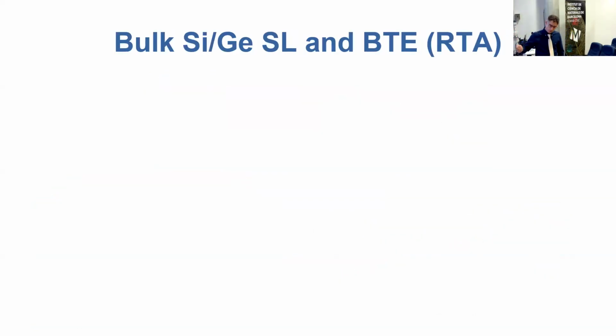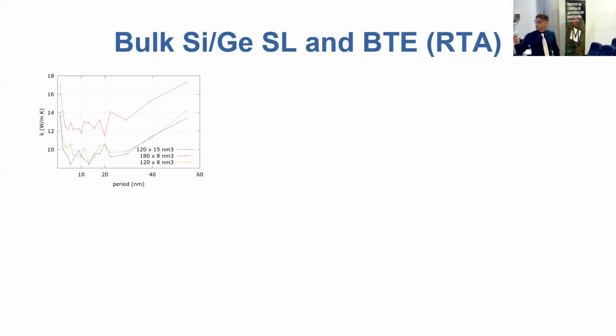Now, we also studied the bulk case, meaning no superlattice nanowire for the silicon germanium, and in this case we performed three different geometrical configurations where we could still observe clearly a transition from the coherent to the diffusive regimes, and of course a slightly higher thermal conductivity for the greater number of phonons present in the 180 nanometers long superlattice.